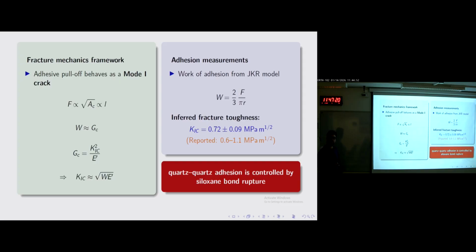This is only valid for my spheres on flats. It's not going to work with the plastic contacts with the pyramids. So if I take only the data from spheres on flats, I can calculate the work of adhesion using this model. It depends on the force of adhesion divided by the radius of the sphere, with other parameters. The radius of the sphere we know, and I can infer the fracture toughness from my adhesion experiments, and you can see that it falls well within the reported range for quartz, 0.72 MPa times meters to the power of half. It falls within the range.